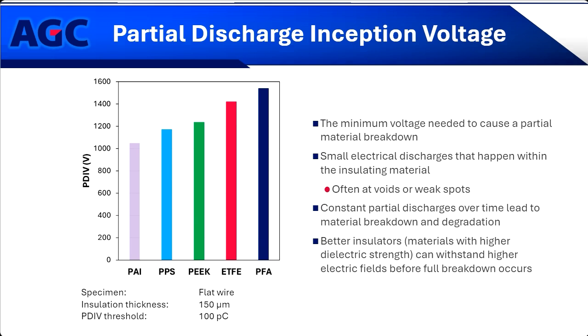So with all of that said, let's look at this data that I've got over here on the left of the slide. So these materials were all measured on the same instrument within the same probably half hour of time. These were coated flat wire, rectangular wire samples. The insulation thickness was around 150 microns, and our threshold to determine what the PDIV was, was 100 picocoulombs.